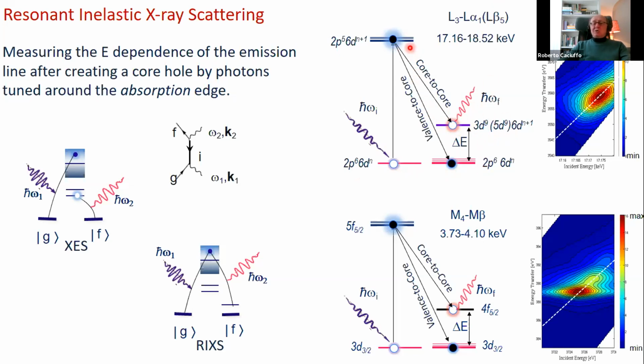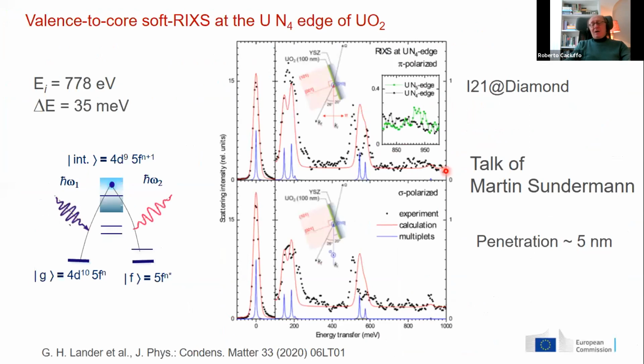And then you can measure the core-to-core signal or valence-to-core. The difference is that in the first case, the final state has a core hole, in the second case, not. Well, experiments have been done at the N4,5 edge.